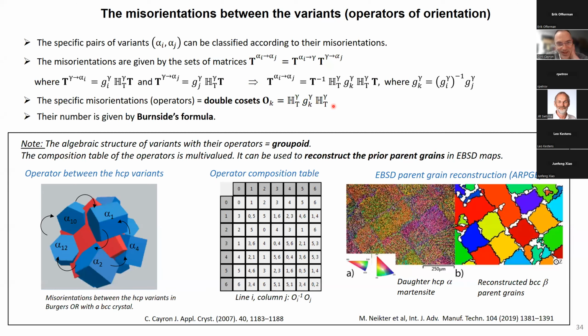It's very technical, I'm sorry for that, but you can calculate the number of double cosets by what is called the Burnside's formula. I will not detail it, but here, for example, is a representation of a BCC, the square in red, to HCP transformation in titanium alloys. You see the hexagons here. We have 12 hexagons. Here you see the variants, and the misorientations between the variants are represented by these arrows here. And mathematically they correspond to double cosets. You can combine these arrows, these misorientations, and make a composition table that is called the groupoid composition table of these arrows. And this is exactly what I used to reconstruct the prior parent grains from EBSD maps, but it's another story. It was just a note here.